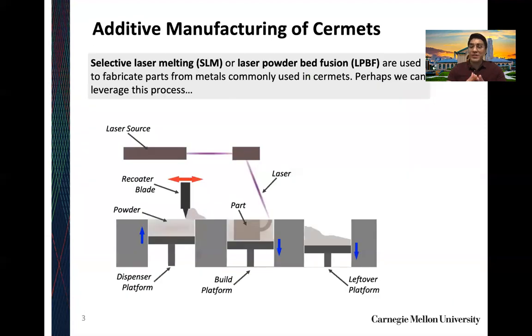And that's where we introduce our established additive manufacturing technique in the selective laser melting or laser powder bed fusion. This process is established for already making or fabricating parts from the same metals that are commonly used in these CERMETs. In our case, we're working with tungsten carbide nickel, and lo and behold, our lab has actually done work with nickel alloys and pure nickel materials. So perhaps we can actually use this existing established technology and leverage it to introduce a new sort of composite material in this machine in order to build up or 3D print CERMET parts.